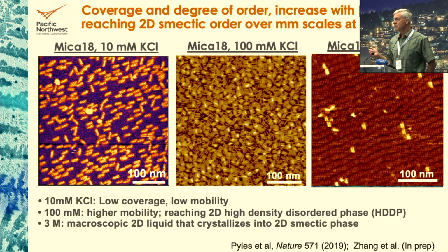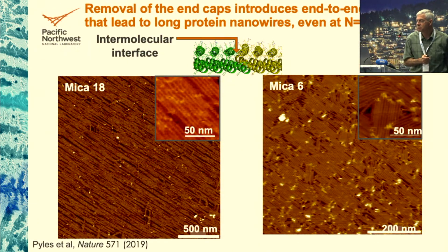Now, I'll mention that there is no smectic phase in 2 dimensions, right? In theory, there should not be a smectic phase where they lie in rows. A nematic phase, where they're all co-aligned but random along the length of the rods, is what would be predicted because the thermal energy is too large for the binding energy within a 2D smectic phase. But of course, these are interacting with the substrate through very specific interactions, so we're stabilizing something that wouldn't exist in 3D. All right, so none of this is in the design, right? We didn't put this in the design.